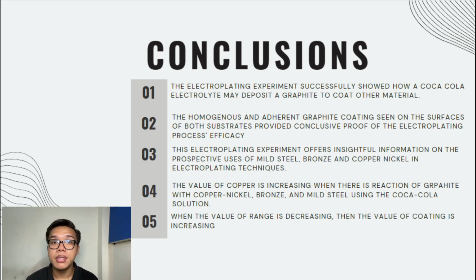The value that has been collected is different between all the specimens. The most value increase on coating is mild steel, then followed by the bronze, and finally, the last place is copper nickel. The ranges that were used in the experiment are 4 cm, which is long range, and 2 cm, which is short range. We can say that when the value of range is decreasing, then the value of coating is increasing. So the range and coating thickness are inversely proportional. The value of the thickness of the coating is variable based on the specimen.